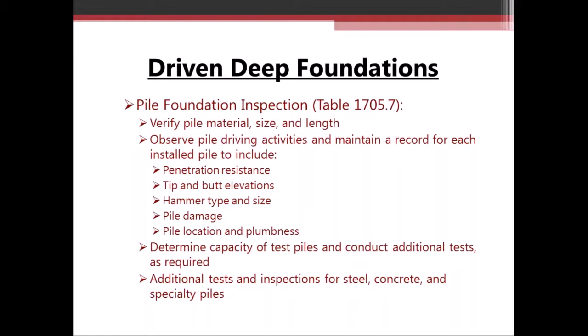So moving on to driven deep foundations. These are typically going to be steel H piles, steel pipe piles, or timber piles that are driven with a large impact hammer to support structures over poor soil conditions. So in the field, the inspector is going to verify the pile material, the pile size and pile length. They're going to observe any driving activities and maintain a record for each installed pile, which will include the penetration resistance, which is how many blows of that hammer it takes to drive the pile over an inch or a foot increment. They're going to monitor or record the top and bottom elevations of the pile, the hammer type and size. Typical hammers in our area consist of diesel hammers, air hammers, or a hydraulic hammer.